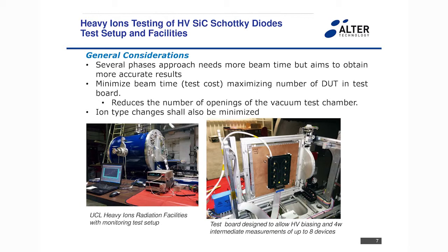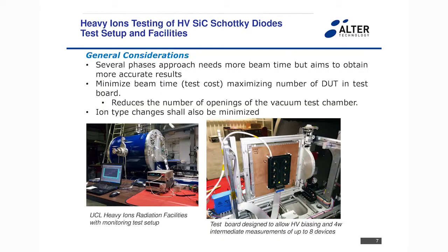Well, general considerations about this test: you need to test a lot of devices and a lot of conditions in the 3 phases, so you have to try to minimize the beam time that leads to a high cost. So we have a picture of a custom test board we designed in order to test 8 devices per board in Louvain and UCL facilities, so you don't have to open the chamber and lose a lot of time in changing the samples, but you have to test with high voltage and take into account some considerations. You need also to think about the LETs you're going to use, because changing from an LET to the next one can take a lot of time, and that is beam time.